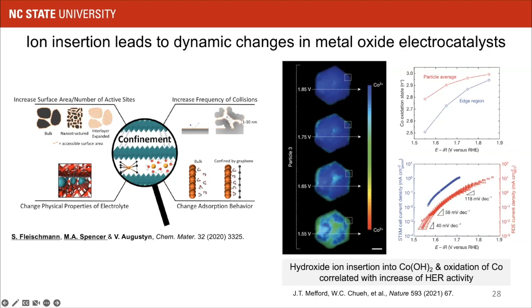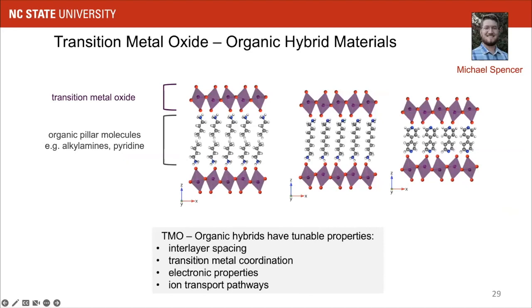And what we decided to study in our group is to use a materials chemistry approach to see if we can trigger the proton insertion either on or off and see what happens to the catalytic process on the surface. So this is work done by Mike Spencer, where we make these transition metal oxide organic hybrid materials. We basically have oxide layers separated by organic pillar molecules. These organic pillar molecules can take on different forms, and they have some nice tunable properties.